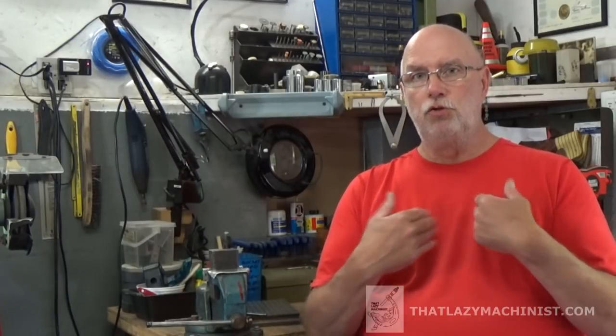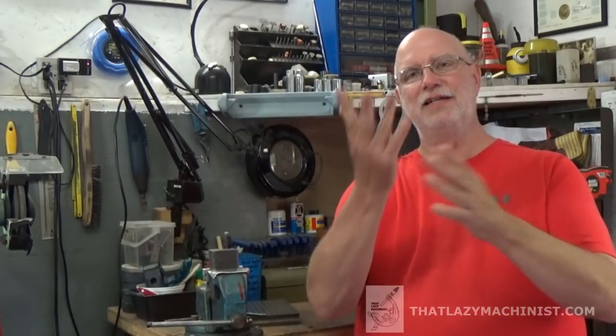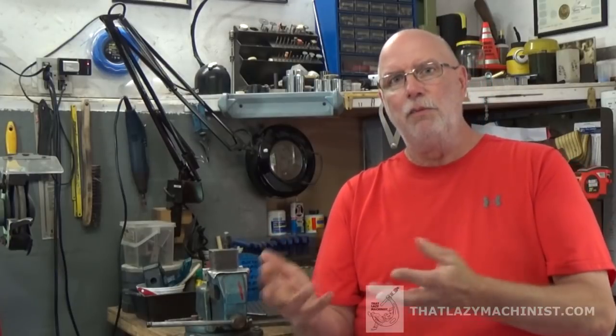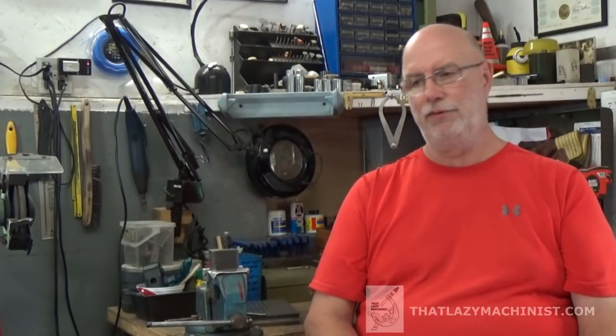The parts that the toolmaker produces often have internal angles. And well, these parts are prone to cracking. The faster it cools, the more prone to cracking tool steel will be. So if I can quench it in oil and cool it down slowly, well, that is a good thing for cracking as well. So we see there's a lot of advantages that the plain carbon steels just don't have. So that is the reason why.